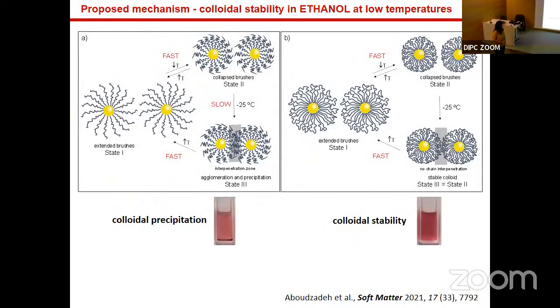This was the last experiment we did with this polymer. We put the nanoparticles in ethanol, we put them in the fridge, and we observed that in the fridge at minus 25 degrees, the linear brushes allow the precipitation of the nanoparticles, but the cyclic ones remain stable for months. Samples are still there, still stable. And then we did some experiments, and we established or explained the results by experiments, and with this mechanism by which, by cooling, the polymer collapses.